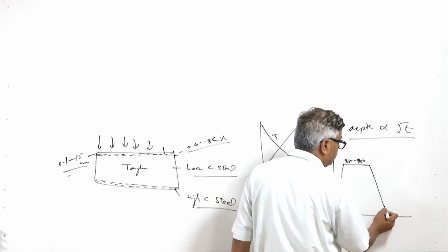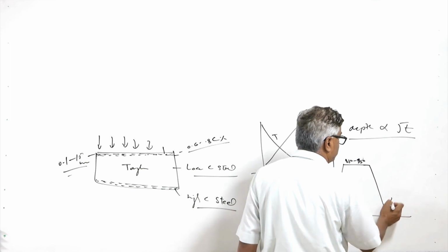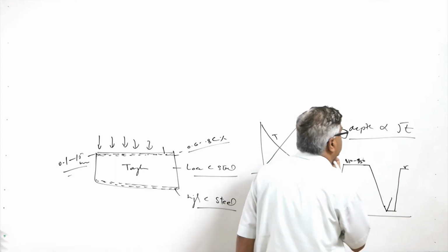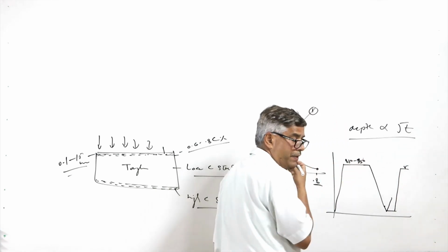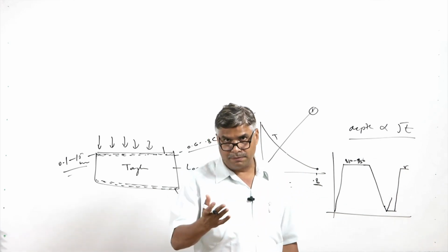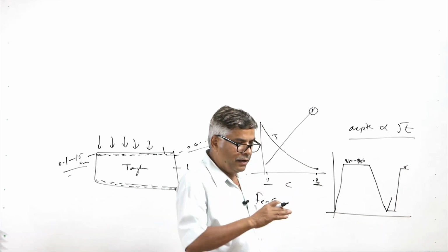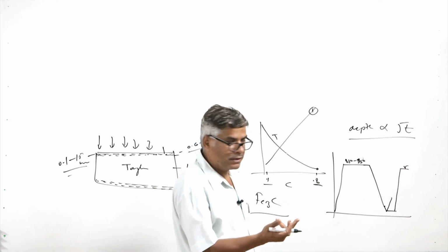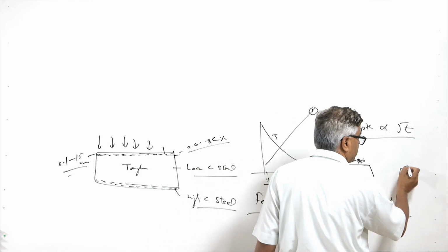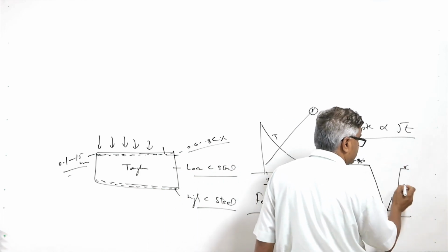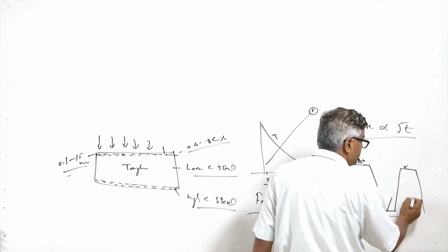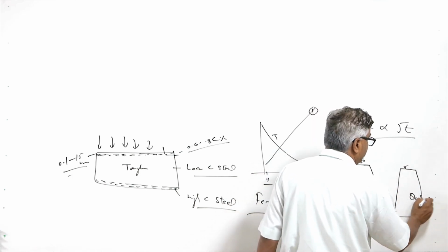After cooling, again it is heated to the austenitic state, so that it forms the austenite. For the carbon content of 0.8%, it will be leading to the eutectoid composition of the steel, wherein the upper eutectoid temperature is 730 degrees centigrade, so heating up to say 800 degrees centigrade will be leading to the formation of the gamma, that is austenite. So once the homogeneous austenite is formed, it will be quenched hard, so quenching will be leading to the formation of the martensite.